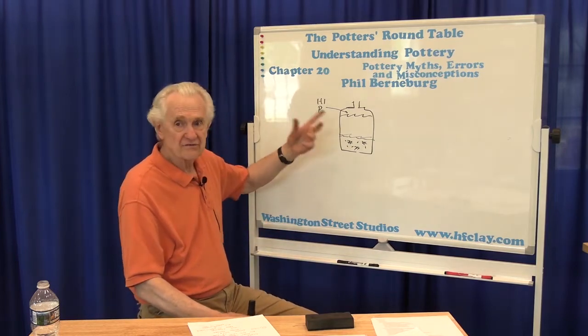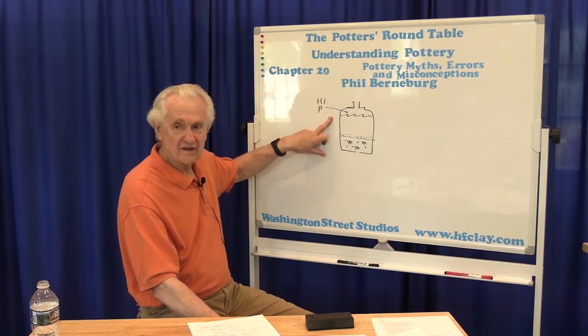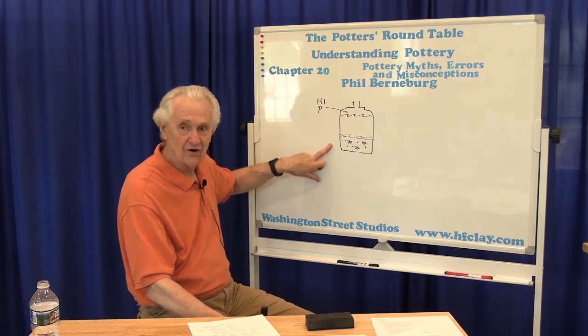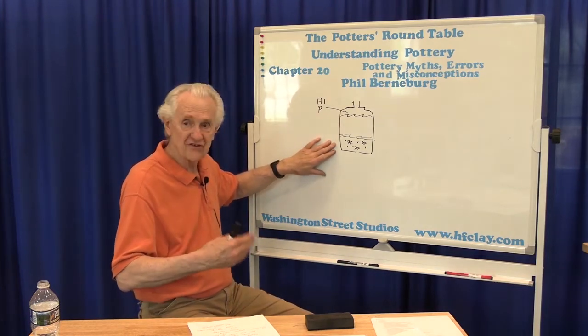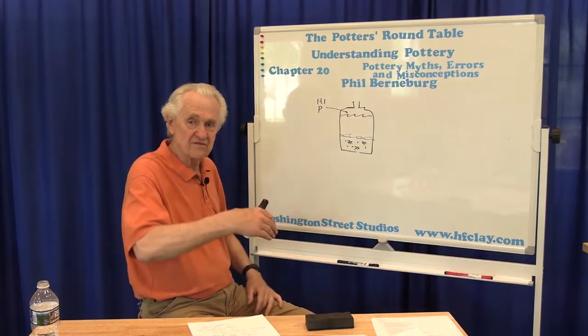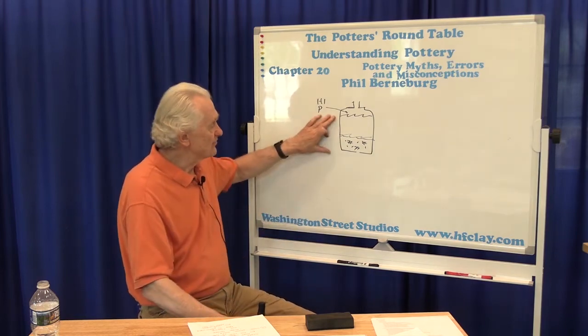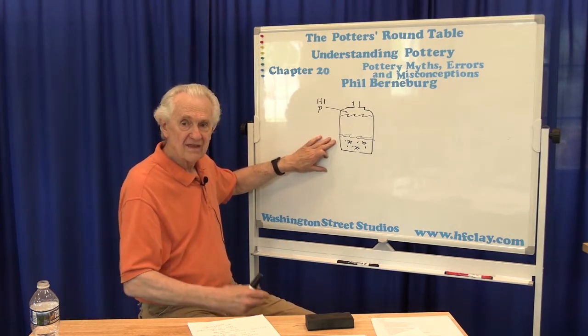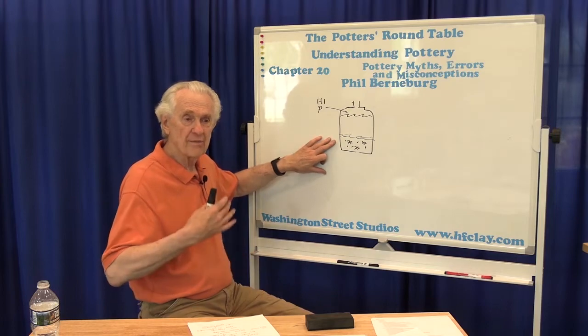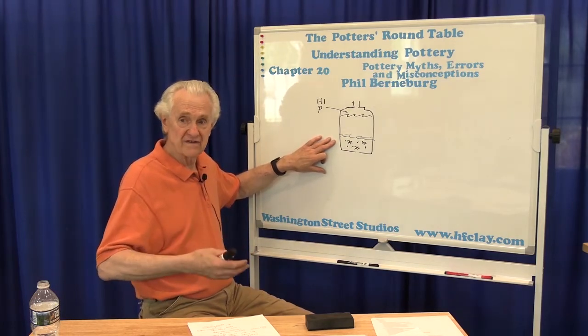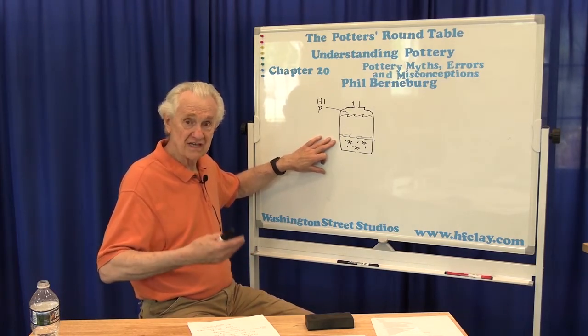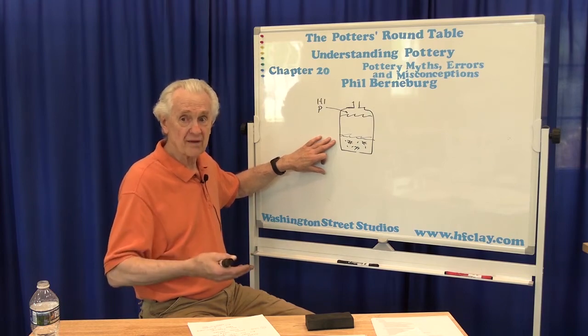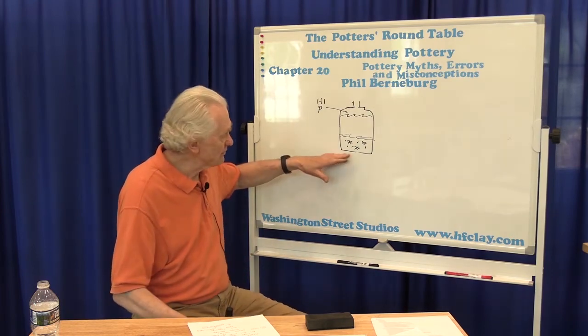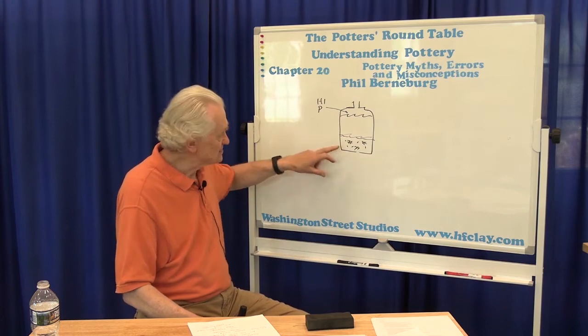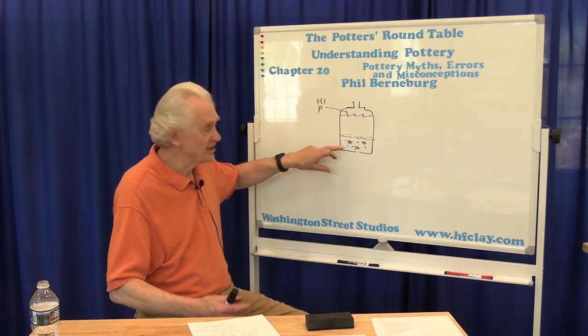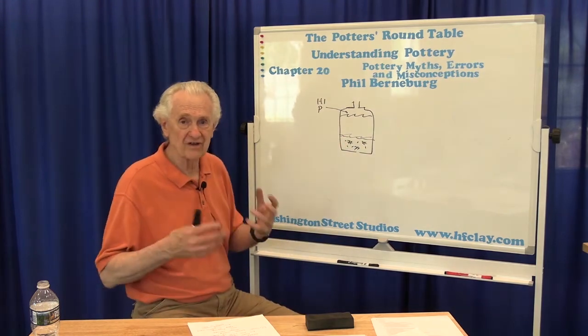So it's sort of the reverse. It's the fact that the level in the propane tank has gotten very low, and that's causing the propane to get so cold that it freezes. It's not the freezing that's causing the problem. And so when the level gets really low and it gets really cold, the propane is not evaporating or boiling as vigorously. It's not producing as much gas, and therefore the pressure drops. So, but it's kind of a misnomer. The tank isn't freezing up. It's just the condensed moisture on the outside because the remaining propane has gotten really, really cold.